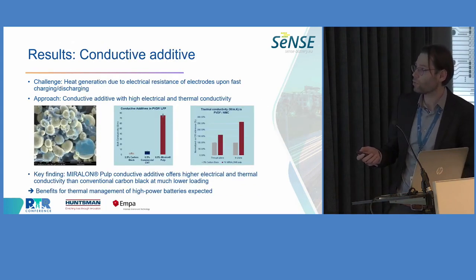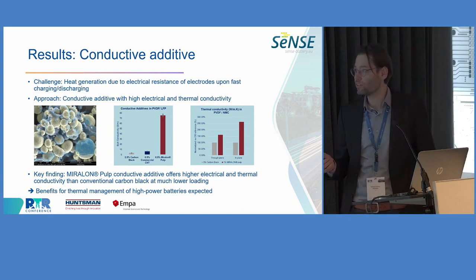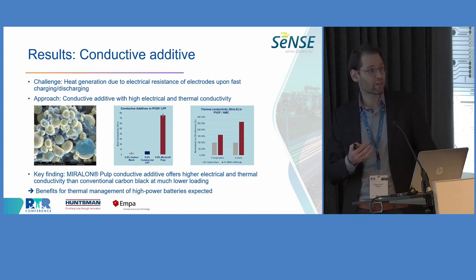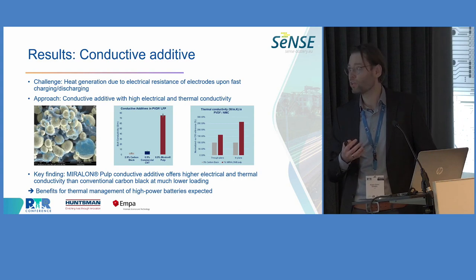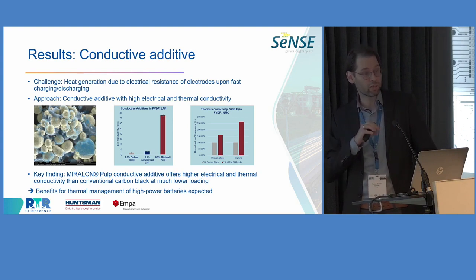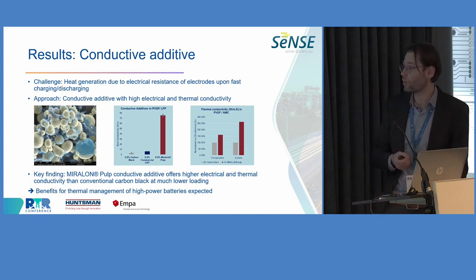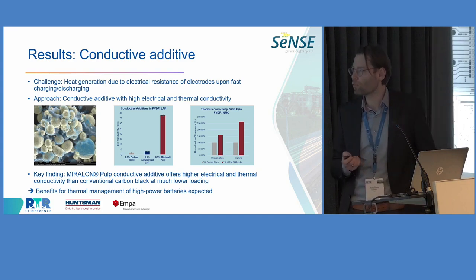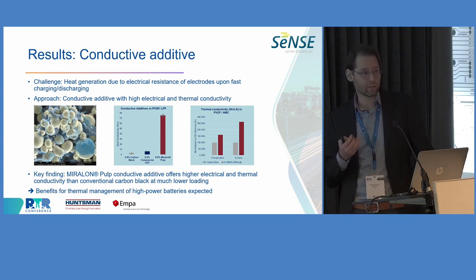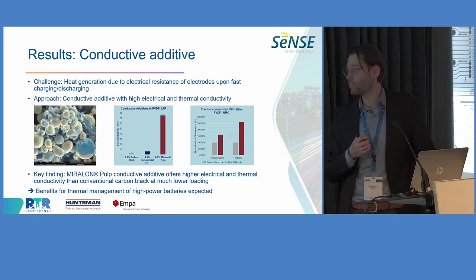The next highlight I would like to briefly discuss, as I mentioned before, is that fast charging is important. One of the bottlenecks here is the heat that is generated. Simon already showed simulation results where you could see that the cells can get really hot, especially on the inside. The larger the cell, the higher the inner temperature reached. Our approach here is to reduce the electrical resistance of the electrodes, because that's a major contributor to the heat generation inside the cell.